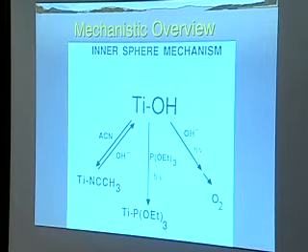On the other hand, you could take another material like this phosphite, and we happen to pick this because it's water soluble. When that binds to a titanium site, it would make this species, and that species would not compete with hydroxide. That is, that binding is much stronger than hydroxide binding. So one would think if you had an inner sphere mechanism and you threw your electrode into this stuff, you would kill your electrode. You couldn't oxidize water, or hydroxide rather, anymore with that.